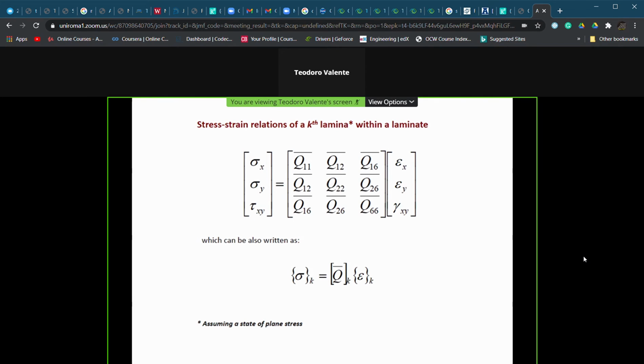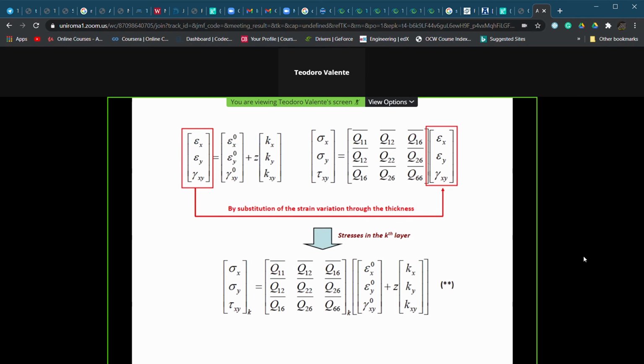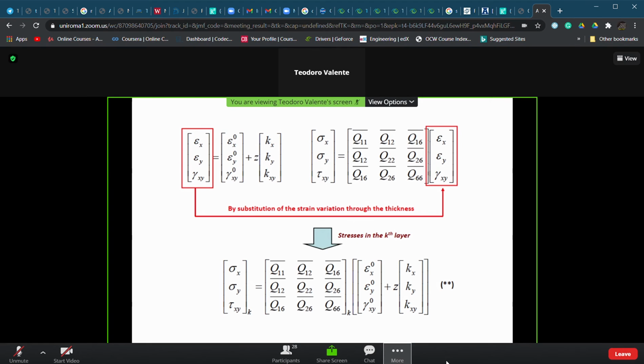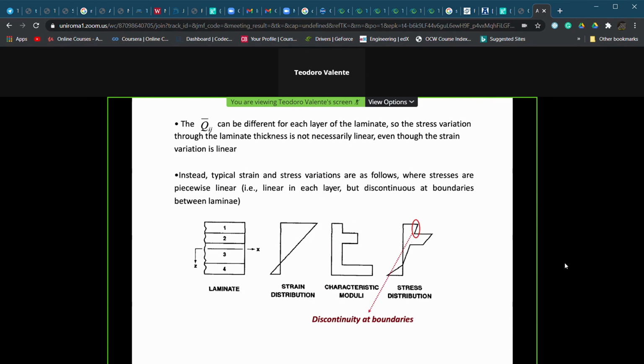And again, also in this case, for the general K lamina inside the composition of our laminate, we can write the equations that we have seen before, and we again make this assumption of the plane stress state. Terms are essentially the same as before, and so we can move through this approach inside each layer and have an estimation inside each layer of the relationship between strain and stresses. And we can expect, going to look into our assumption, you see here, a strain distribution, that is displacement, which is continuous, you see, varying through the laminate, but continuous.